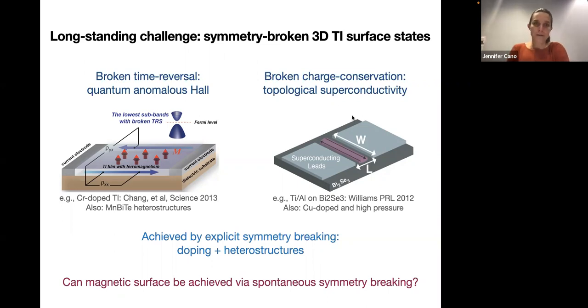interesting phases. So for example, the two canonical things you might want to do, one is to break time reversal symmetry. And if you break time reversal symmetry, you'll open a gap on the Dirac cone surface, and that'll give you a quantum anomalous Hall effect. And this has been achieved. So how do you break time reversal? You introduce magnetism. And so this has been achieved in a few different ways. One is, I think the first realization is by doping a topological insulator with chromium. This introduces magnetic moments into the system and opens a gap on the surface. So if you take thin slabs of this, then you can measure quantized anomalous Hall effect.